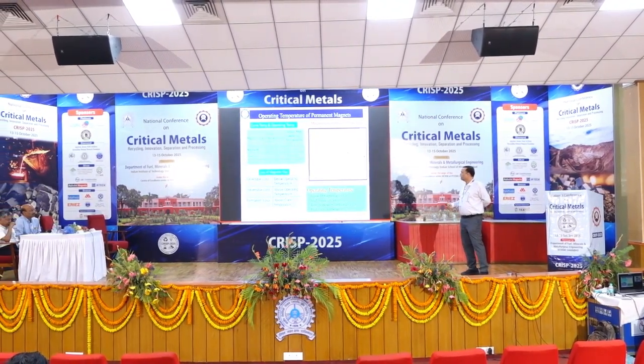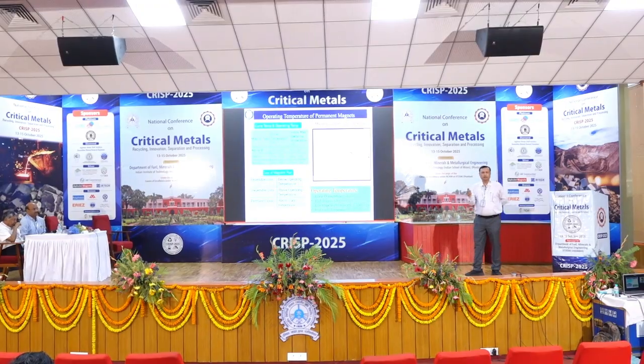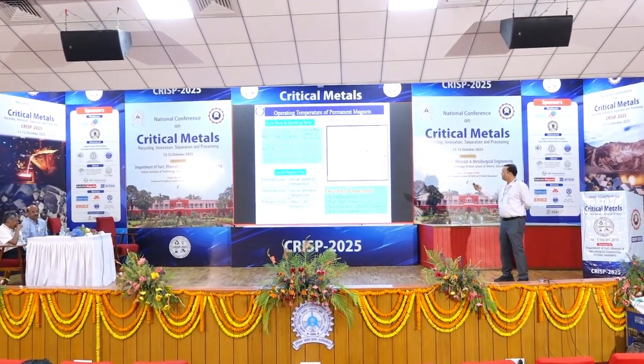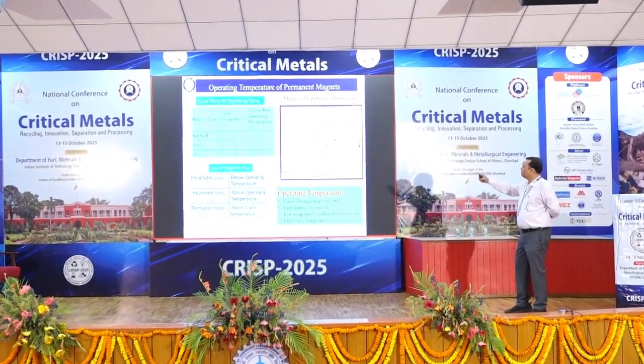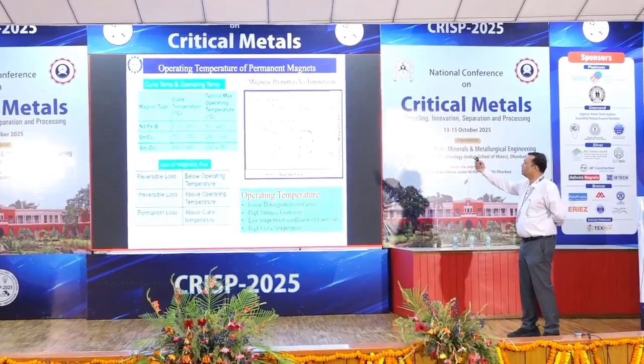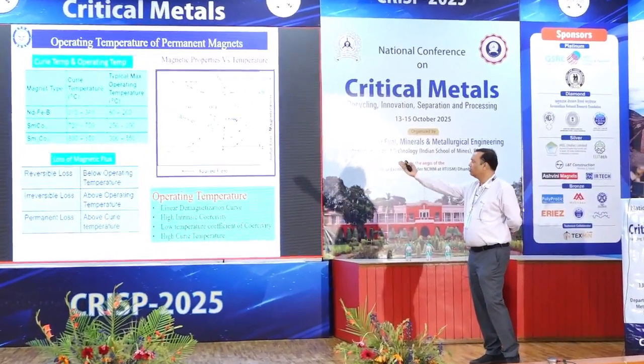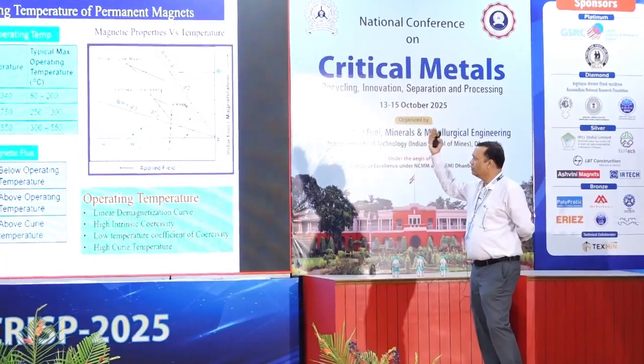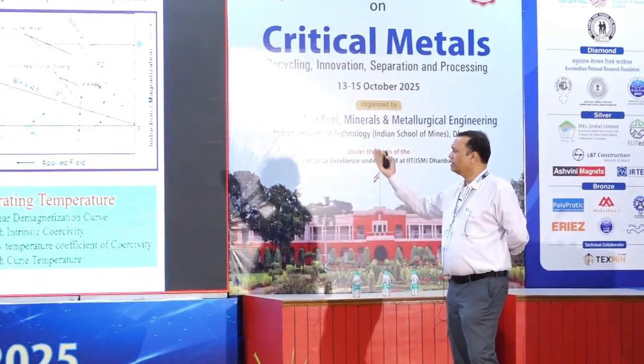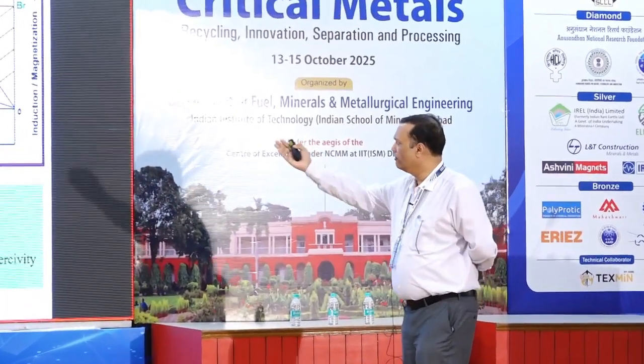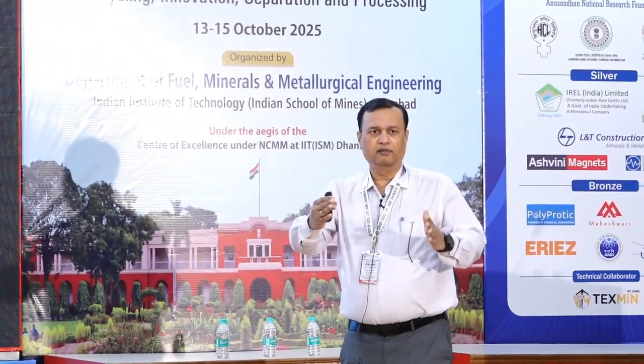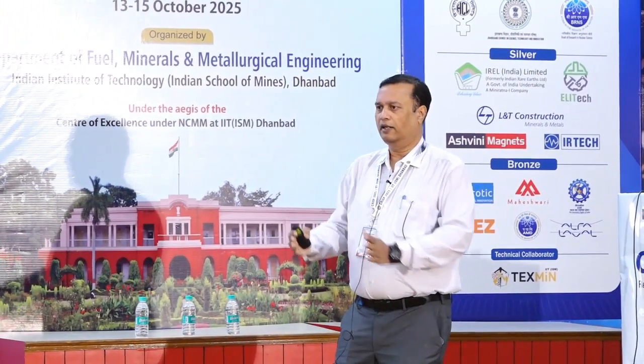But what do we mean by the operating temperature of a permanent magnet? Operating temperature is not the Curie temperature of a permanent magnet. An NdFeB magnet has a Curie temperature of 310 to 340 degrees centigrade, but its operating temperature ranges from 80 to 200. Similarly, Sm2Co17 may have a Curie temperature up to 850, but its operating temperature is limited to 550 only. Why is there a gap between the Curie temperature and operating temperature?